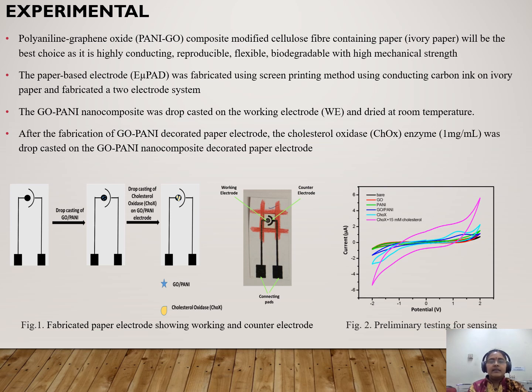So this is the electrode which we made, and these red lines are the wax lines. These are made because the paper is hydrophilic in nature, and if we put buffer solution on this, it can be adsorbed and travel through. Therefore we want to stop that. For that we have used the hydrophobic wax coating, and then we have heated the electrode after coating so that it can make a barrier for not flowing the buffer solution above this area.